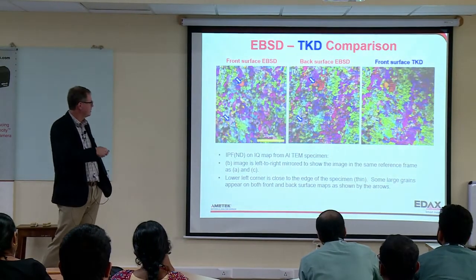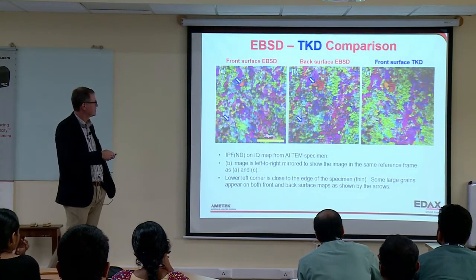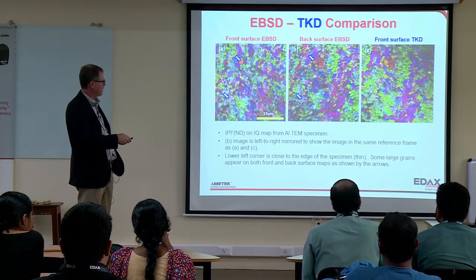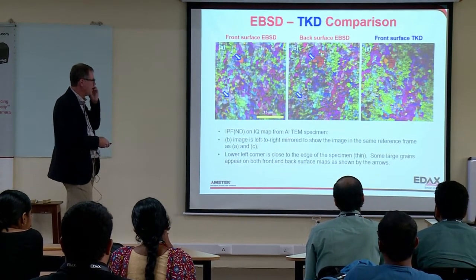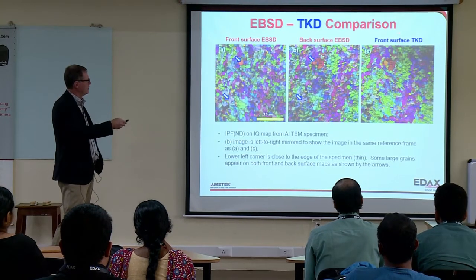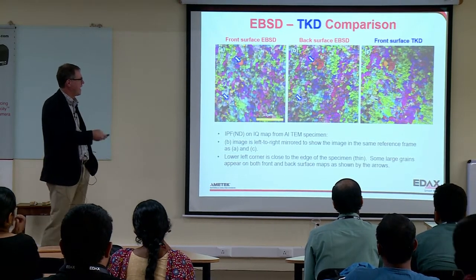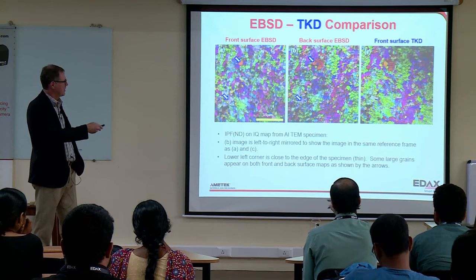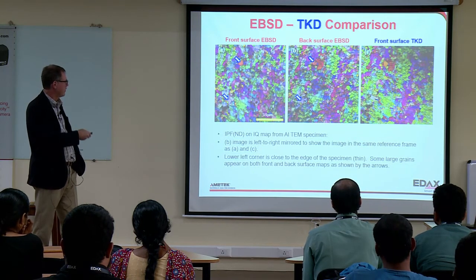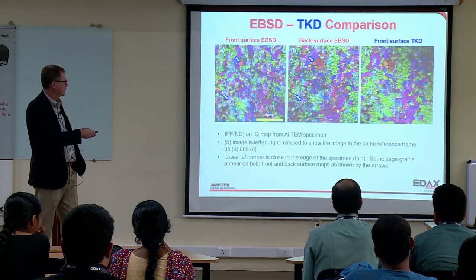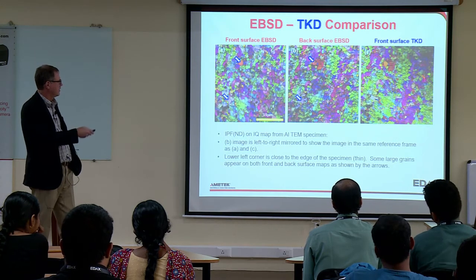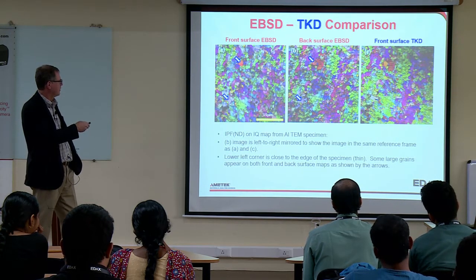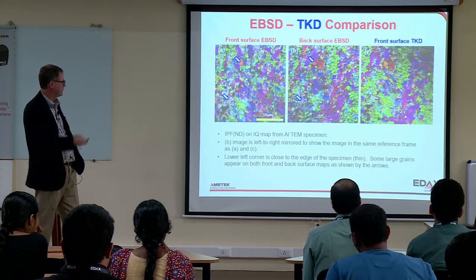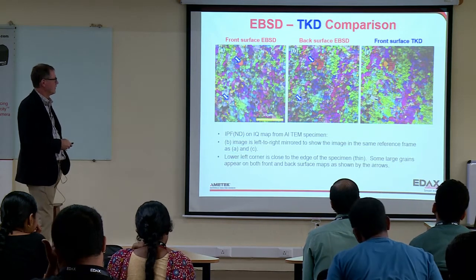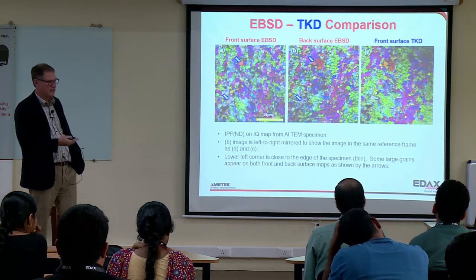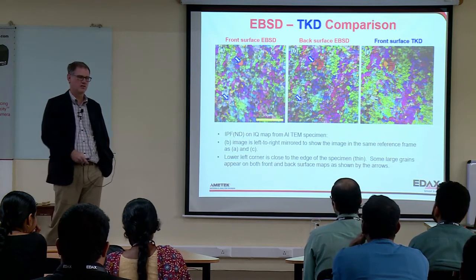So here's EBSD, and this is the front surface. This is if we did the back of that same sample in EBSD. And then this is TKD through the front and out the back. So you can see this one matches this one much more closely, although there are some differences. You can see here and some subtle things here, where this grain actually goes all the way through the sample. So that's another important thing: the TKD signal is from the back edge of your sample when you put it in.